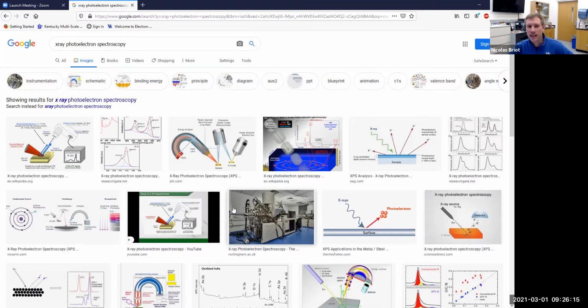Of course, when you send X-rays to the sample, those X-rays are going to penetrate quite deep into the sample. I mean, when you think about X-rays, you think about seeing through things. So the X-rays are going to penetrate quite a bit and generate electrons in the material. But those electrons that it's going to extract have such a low energy that they are going to be reabsorbed right away unless they are very, very close to the surface. And that's why you can have that really great surface sensitivity.